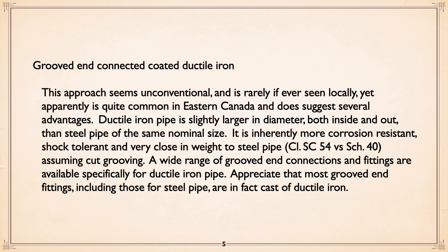So SC54 is ductile, with enough thickness that you can groove it, and Sked 40, of course, is steel, assuming cut grooving. You can roll groove steel pipe, we'll get into that later, but it's not advised. I'm a believer in cut. A wide range of grooved end connections and fittings are available specific for ductile iron. Appreciate that most grooved end fittings themselves, including those for steel pipe, are in fact cast of ductile iron, and we'll get into ductile iron, what it is, later.